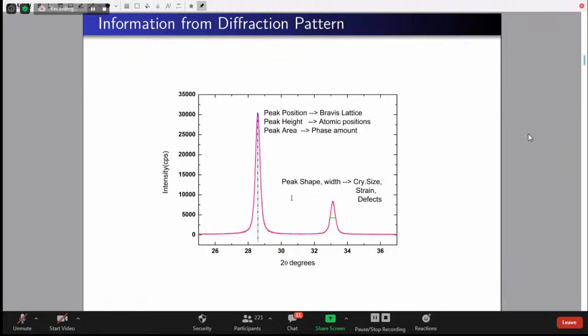So in the entire talk, you will see there are several places where I will talk about how the intensity is getting affected. Whenever in your X-ray diffraction experiment you lose intensity, we should be able to rule out all the other parameters except the sample ones. Then, if we could avoid all of them, we can attribute the loss of intensity only to the sample.